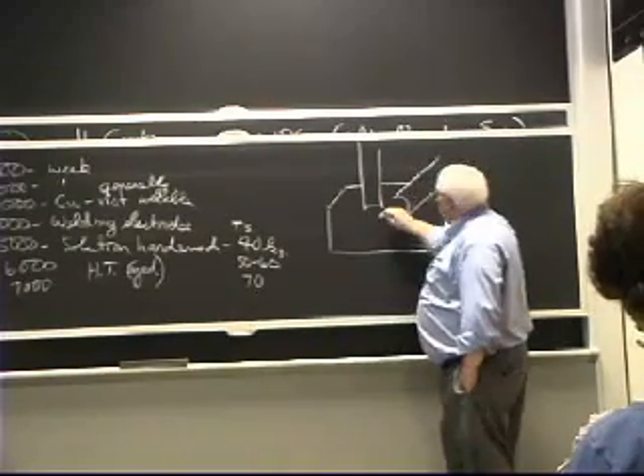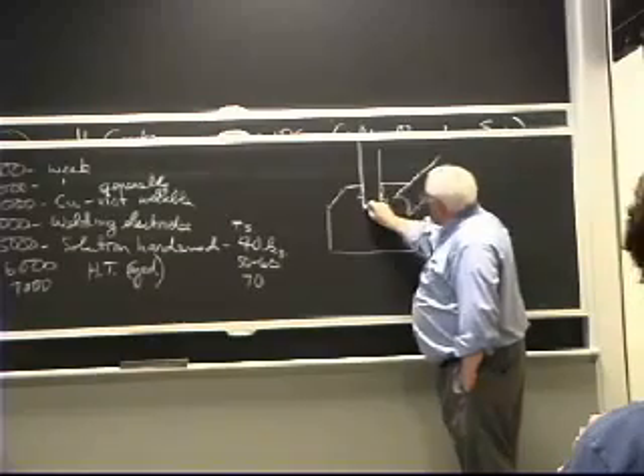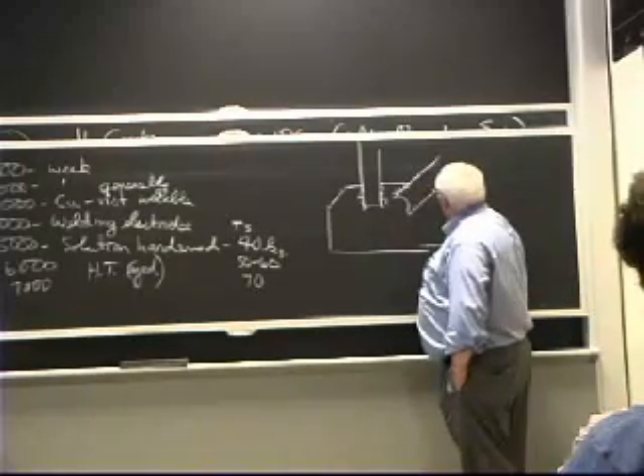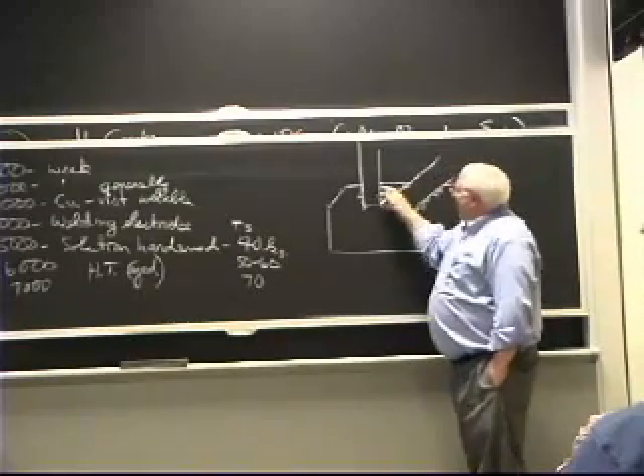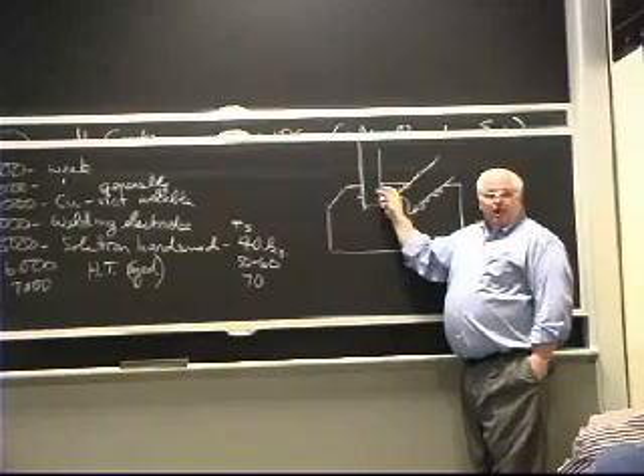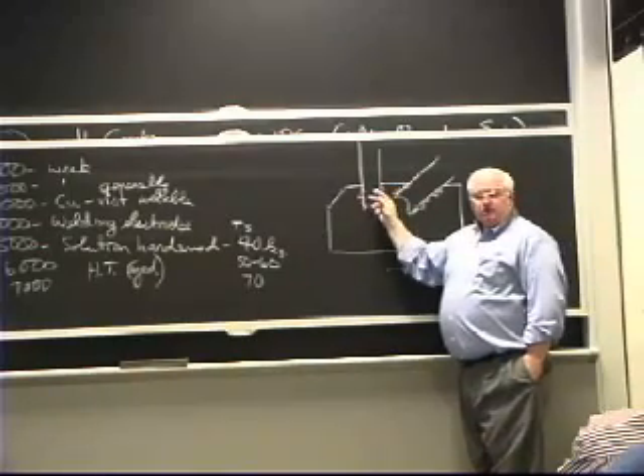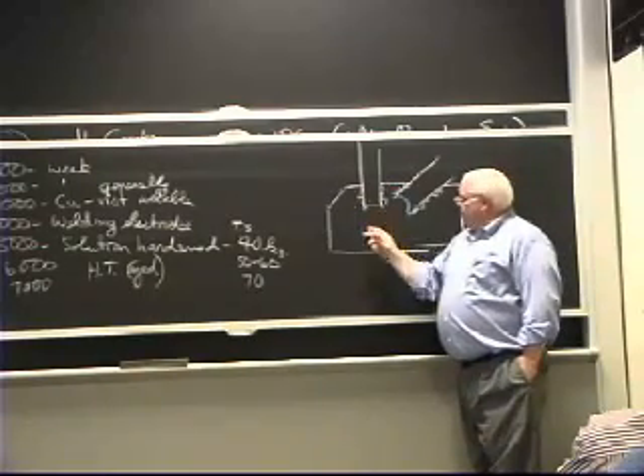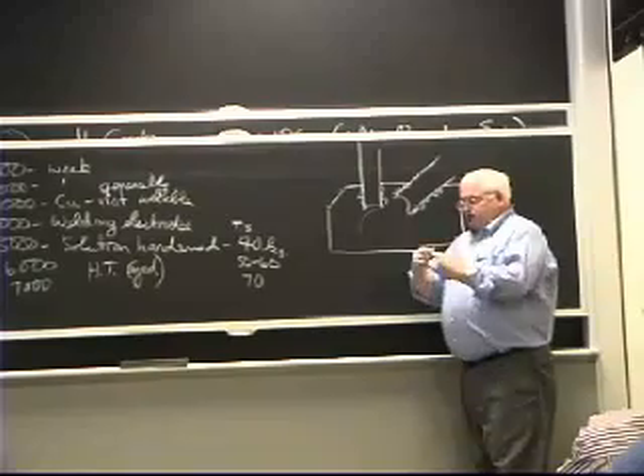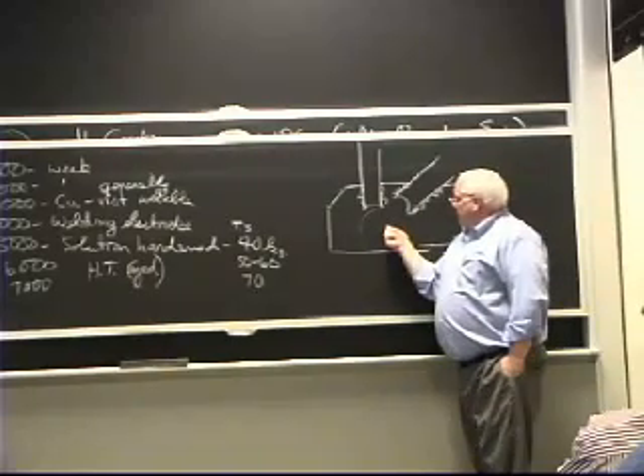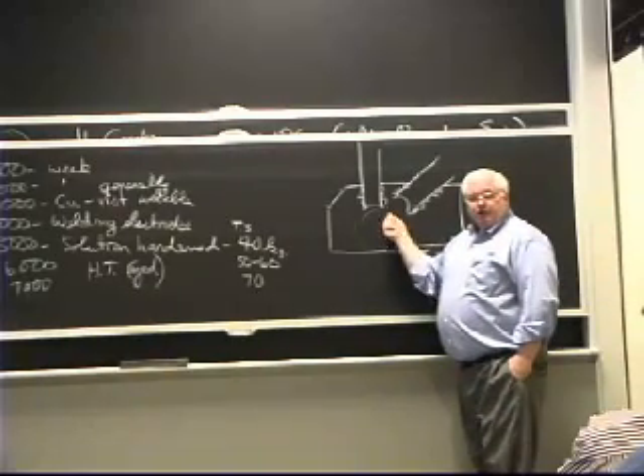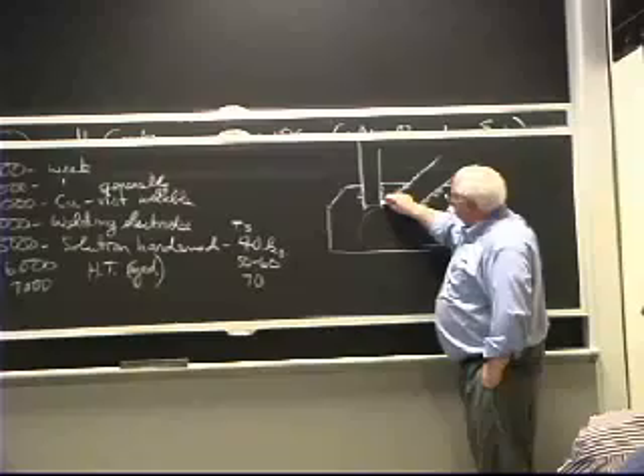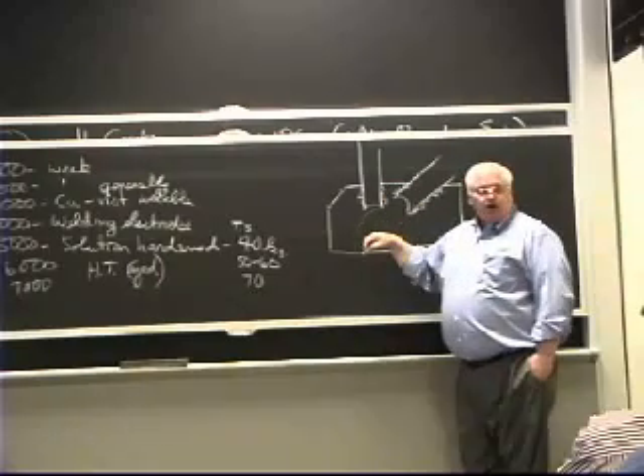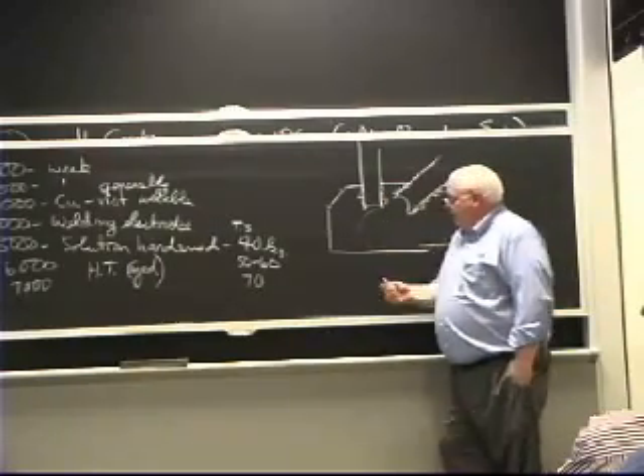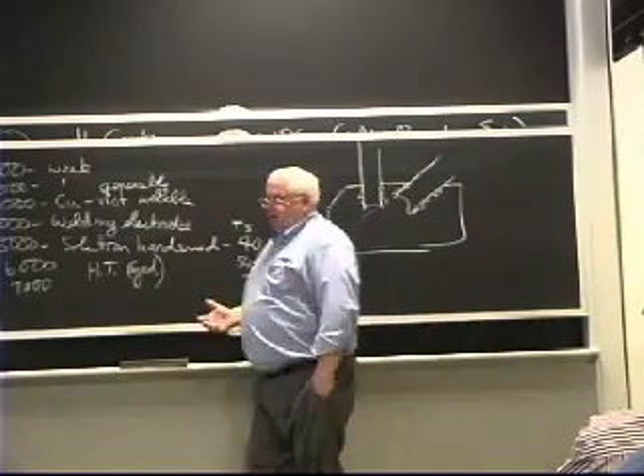I might have another one down here, and I'll put welds, fillet welds in over here. If I do this properly, I can get just as much strength even though the weld metal is half as strong as the base material, because the intersection of all these tubes comes into a gusset plate that bears the stress. Then I can have a nice long fillet weld compared to anything I just had along the length here. It's a more expensive structure, more welding, but I can use the high strength aluminum alloys so far as that goes.